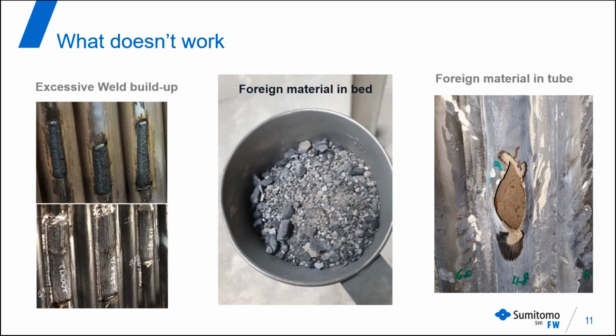On the other hand, when the bed management of the fluid bed boiler is not good, there starts to be a lot of coarse material in the bed, which results in higher erosion when the coarser material is getting in and eroding this lower part of the furnace tubes.